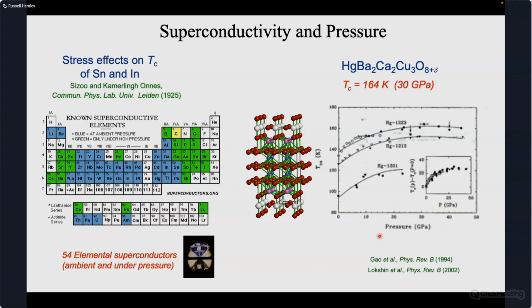An important aspect of this also is just using pressure to tune superconductivity to maximize it. And this was for many years the highest TC on record. This TC in this mercury barium cuprate material with a TC of about 164 Kelvin at 30 GPa.